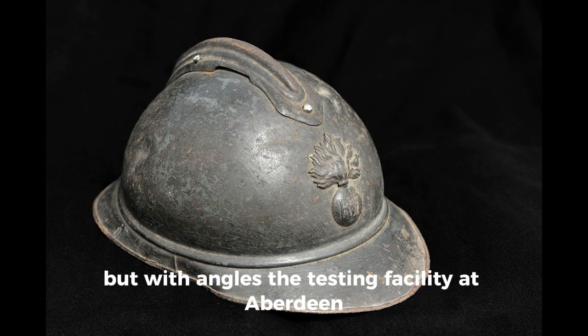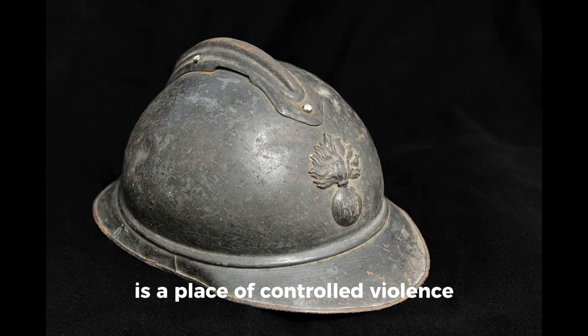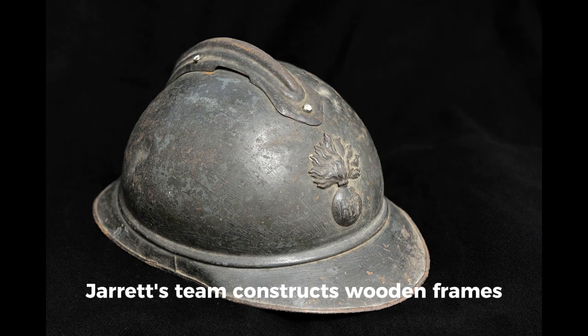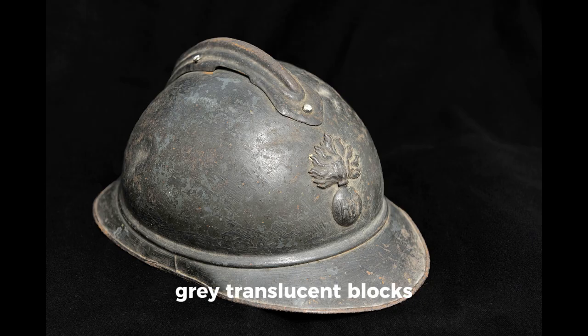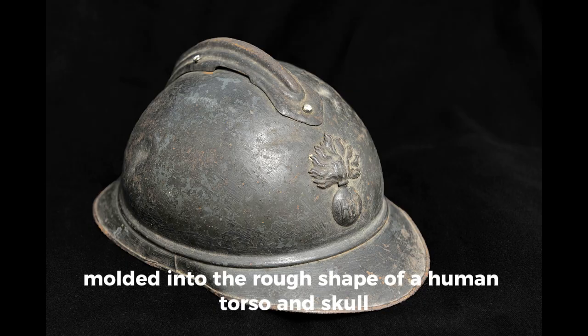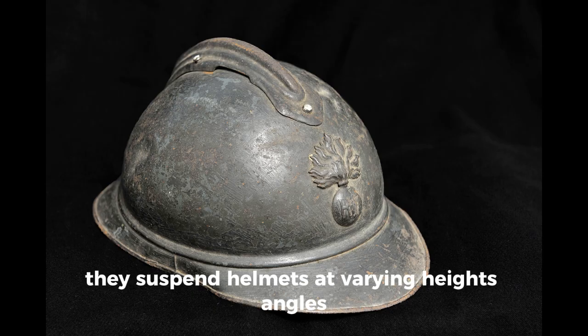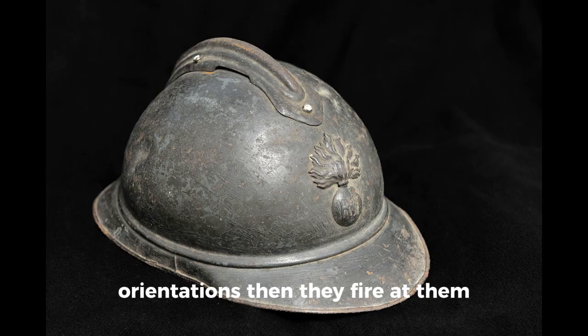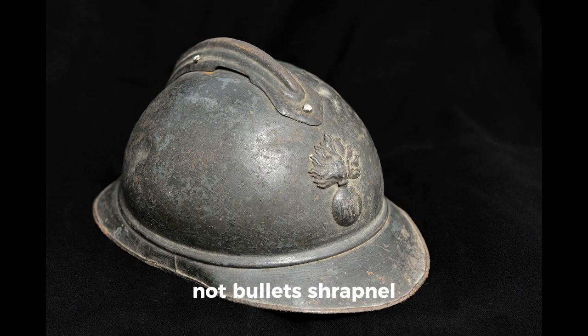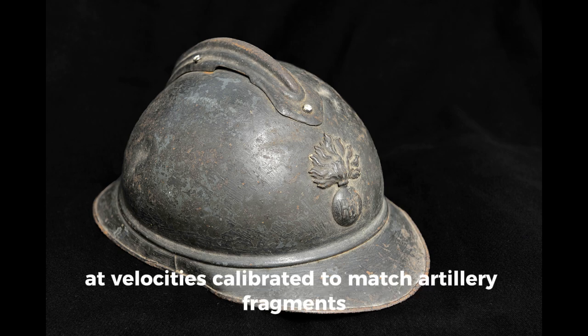The testing facility at Aberdeen is a place of controlled violence. It is where theories go to be destroyed. Jarrett's team constructs wooden frames fitted with ballistic gelatin, gray, translucent blocks, molded into the rough shape of a human torso and skull. They suspend helmets at varying heights, angles, orientations. Then they fire at them. Not bullets, shrapnel, irregular chunks of steel propelled by compressed air at velocities calibrated to match artillery fragments. 1,200 feet per second, 1,500, 1,800. Some tests use ball bearings.